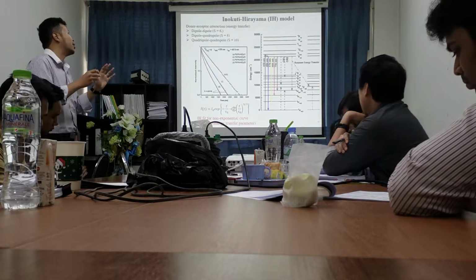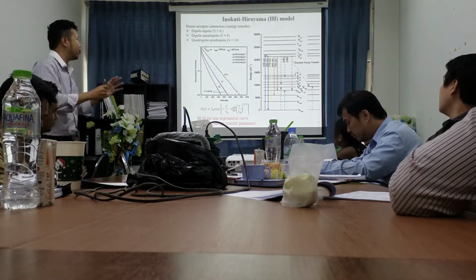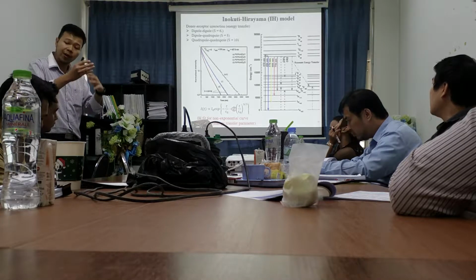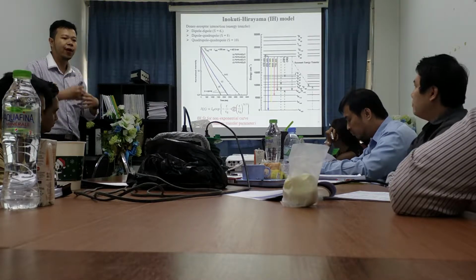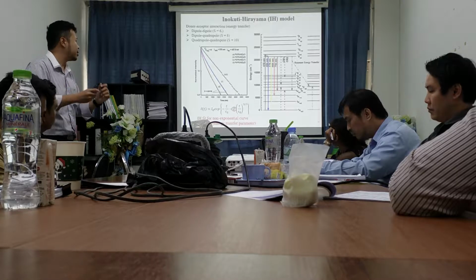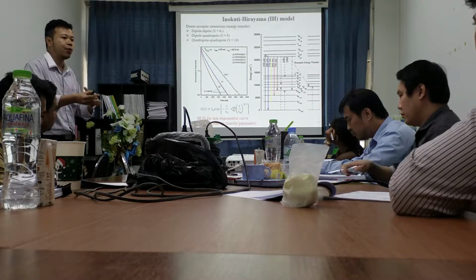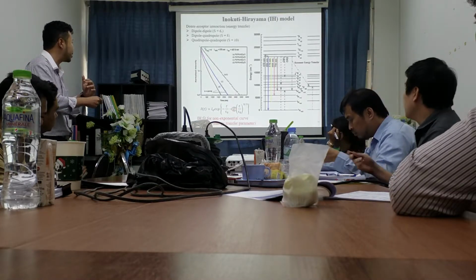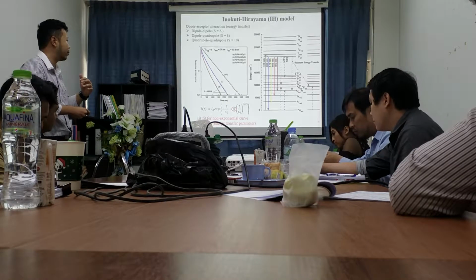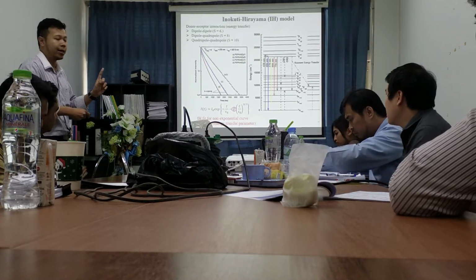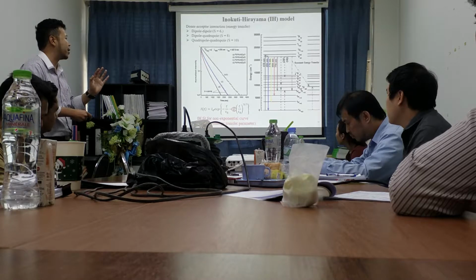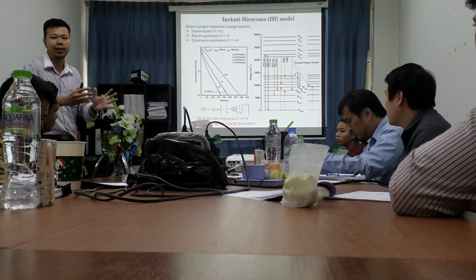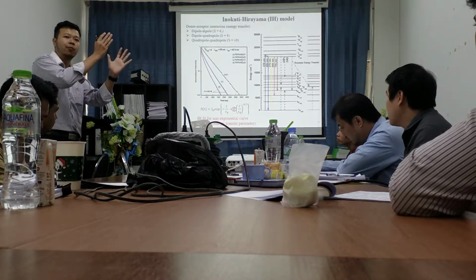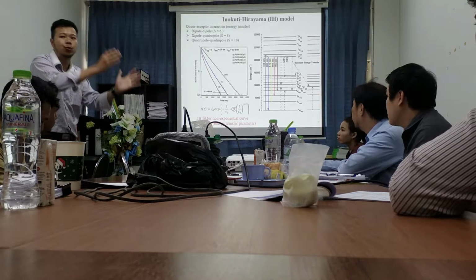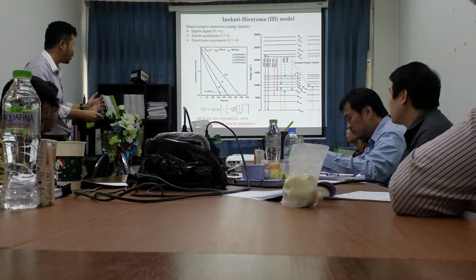Next is the Inokuti-Hirayama model. When we measure the luminescence decay curve, if we find a non-single exponential, that means we need to fit the non-single exponential, which is this model, to find the Q parameter. The Q parameter is the energy transfer parameter that tells us about the probability of the energy transfer from one lanthanide ion to another lanthanide ion.